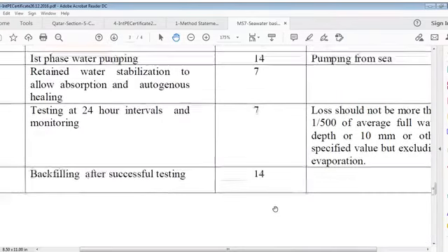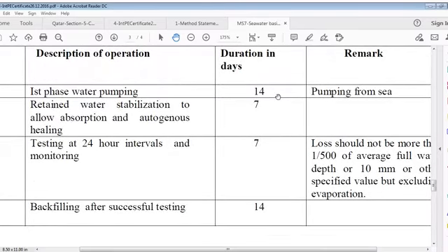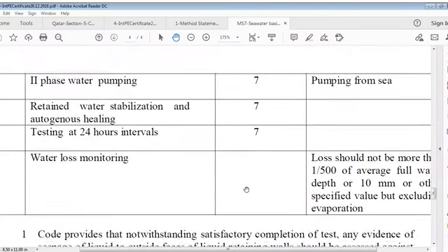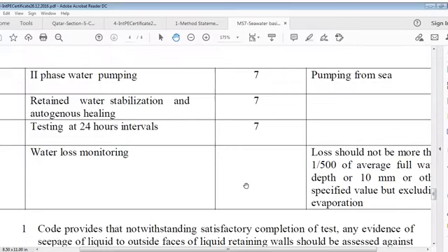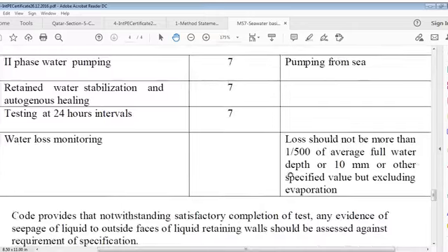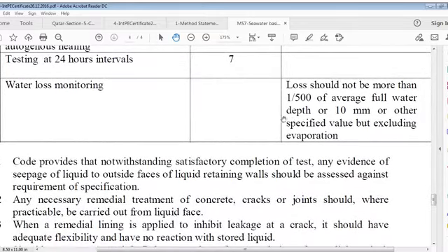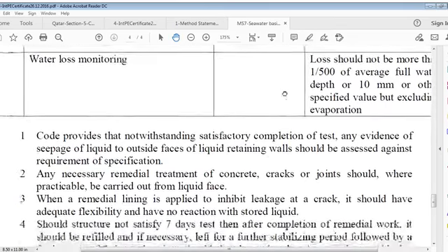Now second phase. This was the first phase, 14 days for filling and then retention for 7 days, testing for 7 days, and backfill after successful testing. Second phase, water pumping, 7 days, pumping from the sea, retention period or retained water stabilization and autogenous healing 7 days, and testing at 24 hour intervals 7 days. Water loss monitoring, loss should not be more than 1/500 of the average full water depth or 10 mm or other specified value, but excluding evaporation.